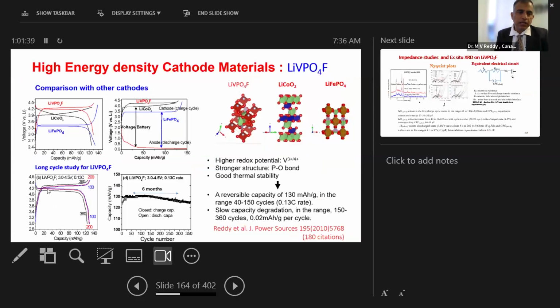Typically, as you can see clearly, these are charge and discharge potentials and reasonably good, nearly 6 months. It means the long-term stability is really good. So as you can see clearly, nearly a 4.2 volt cathode we can get. So you compare to the other three types of cathodes, top lithium vanadium fluorophosphate has higher energy density expected because of the higher voltage. I'm talking about this in 2010.